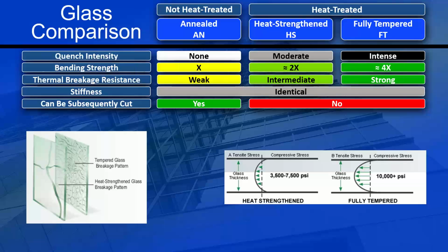So ANHSFT: annealed, heat strengthened, and fully tempered. Annealed glass is what all float glass starts off as. Heat strengthened and fully tempered are fabrication processes done to make that glass stronger and more resilient, or to make it into safety glass, for example. The bending strength of heat strengthened glass is approximately 2 times that of standard annealed glass, and fully tempered glass is roughly 4 times that of standard annealed glass. With regards to cutting, the glass needs to be cut before it is heat strengthened, before it is tempered. I have heard stories of folks polishing or grinding or cutting heat treated glass, and it is not something that as a glass manufacturer we recommend.